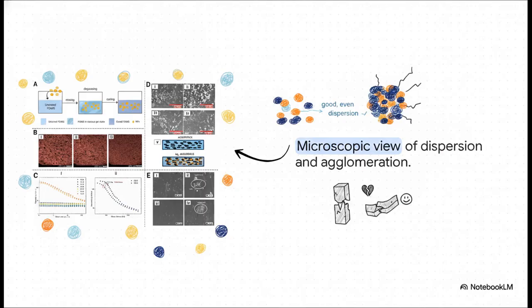However, getting that perfect network is tough. On one hand, you can have good even dispersion, but on the other hand, you can get agglomeration. If scientists add too many nanoparticles, usually above 8 to 10% for some materials, the particles clump together into these big voids and clusters. When they clump, the material loses its flexibility, gets brittle, and, well, totally ruins the whole point of using rubber in the first place.